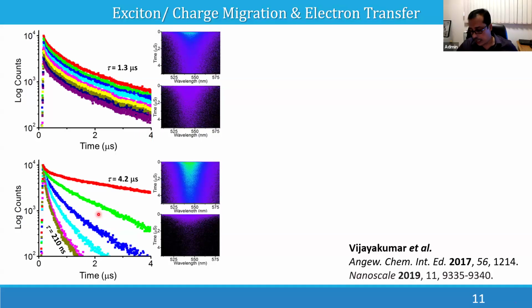Yeah, so it can travel from one point to another point within the film, and we tried to understand what is basically happening and what is the photophysics behind this. Okay, so it is slightly deeper photophysics. I will try to explain in a relatively simple manner. So in the nanocrystal solution, it is isolated nanocrystals. So when we add more and more C60, it will go and attach to these nanocrystals, and that will quench the nanocrystal. So if the C60 is attached, that will completely quench the nanocrystal. But if it is not attached, okay, if some nanocrystals are free, they will emit just normally.